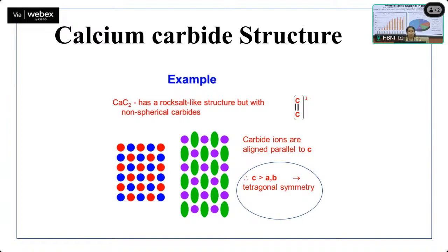Okay, so ideally by virtue of stoichiometry you can say that it is not 1:1, but we count it as 1:1 because carbide exists as an anion. It is not C and C, it exists as a single lattice point, a single anion. And it also has a rock salt structure. Your carbide ion occupies the face centered position, which is the corner and the center of the faces, and calcium occupies the octahedral voids, which are the edge centers and the body center.